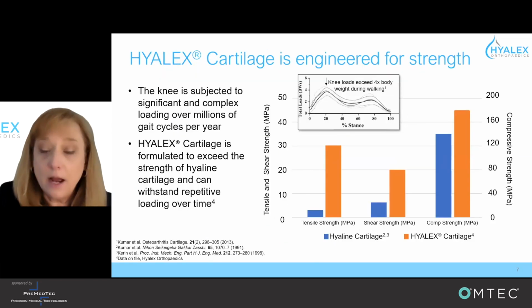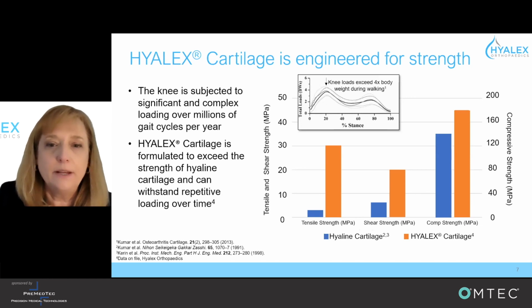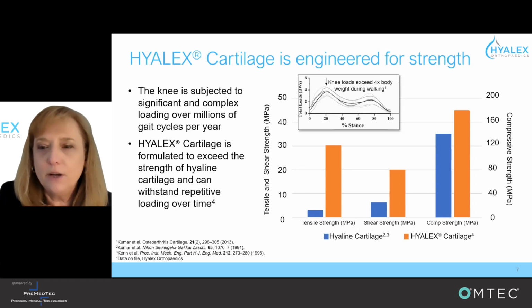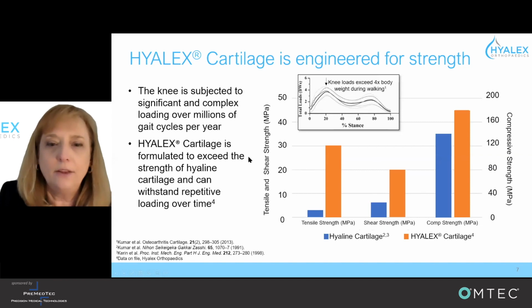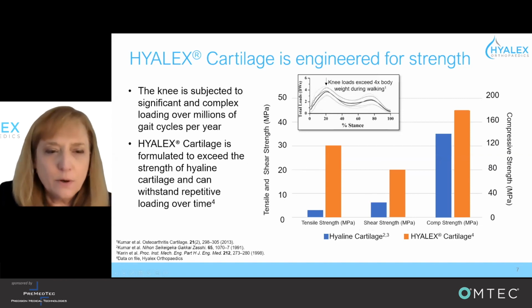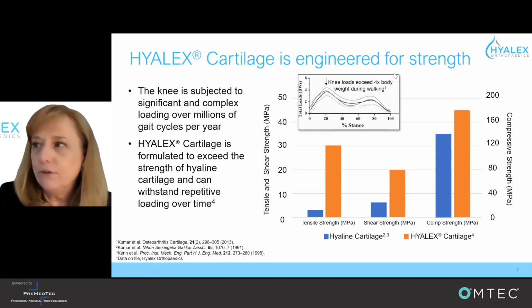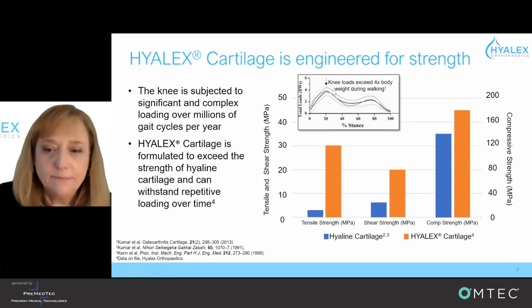Unlike other polymers like hydrogels, Hyalex cartilage is formulated to be stronger than the native cartilage so that it will withstand the millions of loading cycles experienced in a joint over time. As the figure on the right shows in this slide, the material strength in tension, shear, and compression all exceed the properties of healthy native cartilage. This is important in a joint like the knee, which has complex motions that involve both rotation and translation. Knee loads exceed body weight by several times just when walking. Other activities such as climbing and jogging result in further elevation of these knee loads.